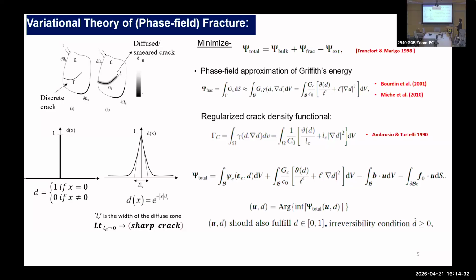So a sharp crack is represented by this. If you just compare the equivalent damage description of a sharp crack, then on this x-axis, at x equal to 0, we have d equal to 1, which is a completely damaged or cracked material, and everywhere else d is 0. So that's the sharp representation. But in the domain of phase field, we approximate this by a smoothing of this d variable. So instead of the sharp jump from 0 to 1, we describe this jump over a length scale l_c, and this jump is very smooth. Again, d equal to 0 is uncracked and d equal to 1 is fully cracked material, and this holds true. But the only difference is that now it's a smoothened approximation, which is controlled by this length scale parameter l_c. This is a very important characteristic parameter in the domain of phase field fracture.